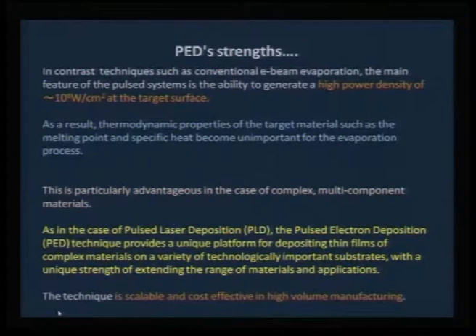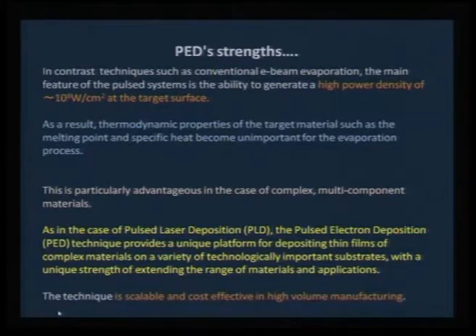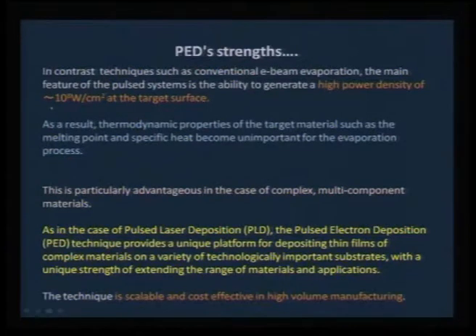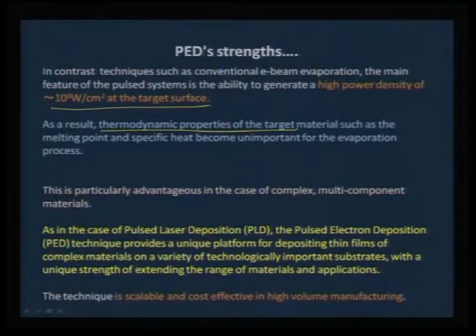PED has strengths compared to PLD. In contrast to conventional electron beam evaporation, the main feature of this pulse system is the ability to generate a high power density of 10^8 watts per centimeter square at the target surface. This means thermodynamic properties like melting point and specific heat become unimportant, since the high-energy pulse overcomes all these barriers, allowing evaporation of virtually any material.